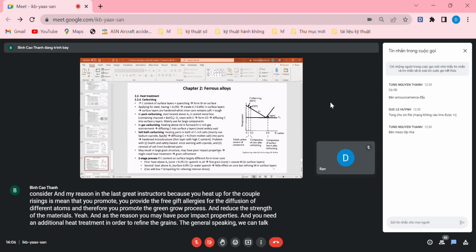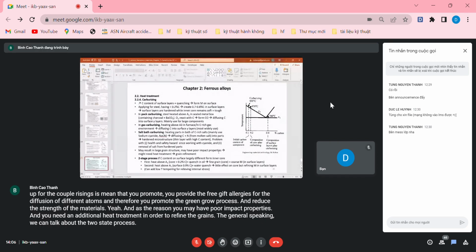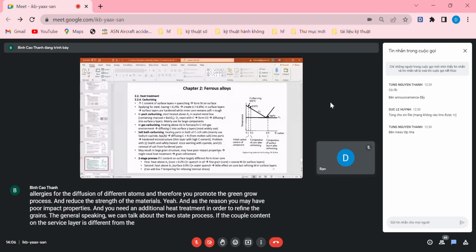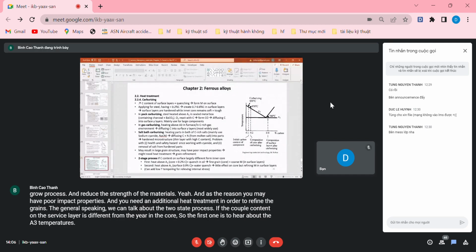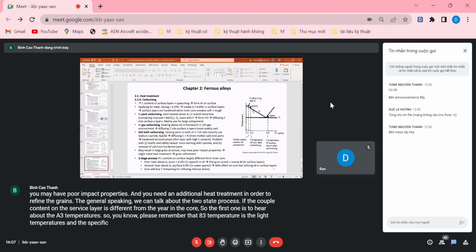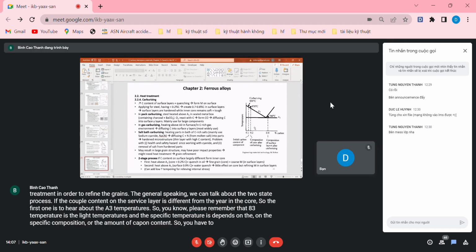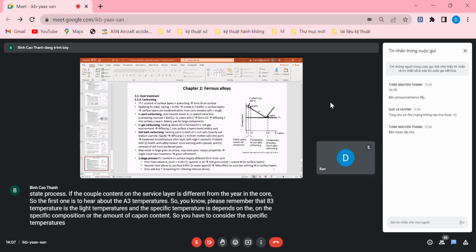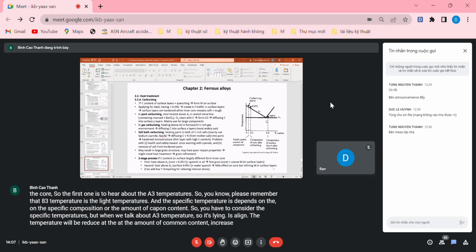Generally speaking, we can talk about a two-stage process, if the carbon content on the surface layer is different from the inner core. The first is to heat up above the A3 temperature. Please remember that the A3 temperature is a line, and the specific temperature depends on the composition or the amount of carbon content, so you have to consider the specific temperature. The temperature is reduced as the carbon content increases up to the eutectic point.